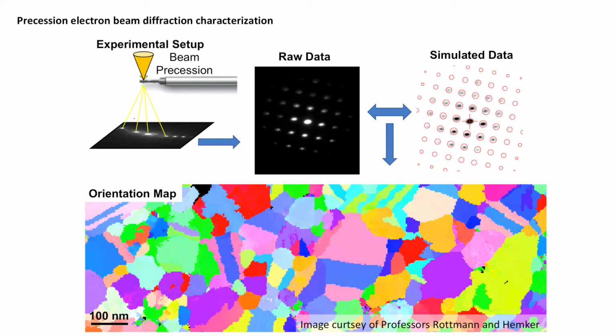And we applied PED to study the microstructure of the shear band in titanium. The micrograph you see here is a virtual bright field image from PED. This is very similar to the regular bright field TEM image. Within the shear band, you can see many nanocrystalline grains. Here are a few examples, like here, here, here, and here.